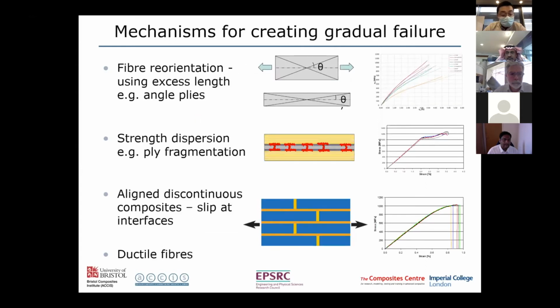So we looked at a number of different approaches to this. We looked at whether we can create this additional strain by means of fiber reorientation. We have angle plies, and they can scissor. That produces additional strain over and above the strain in the fibers, giving a nonlinear response and some additional strain and more gradual failure. We looked at strength dispersion, for example, fragmentation in plies.